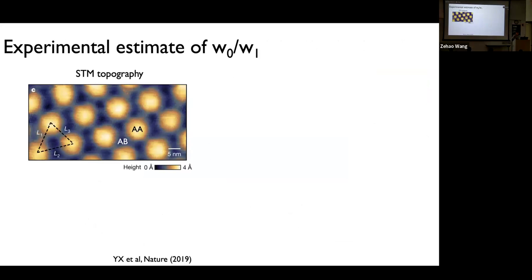Because it was brought up yesterday, I just want to quickly mention, because yesterday I think Eve mentioned ways to extract that from a numerical or theory point of view, I just want to mention two ways that some people think allow you to extract this W0 over W1. Of course, I'm biased. The best way is to use STM, but it's still not perfectly correct, which is to look at the area, this bright region. Basically, you have the A atom in the top graphene layer and the A atom from the bottom graphene layer stacked right on top of each other.